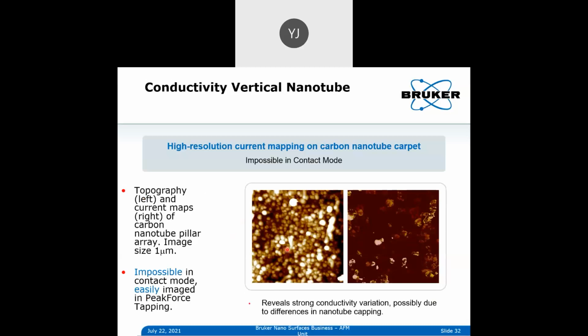Another example is a forest of nanotubes. All these nanotubes you see here are standing facing you, so they are like pillars, right? On top, you sometimes see metal particles like nickel or whatever that's used during the growing process. This is the topography. If you have to image this kind of very delicate sample with contact mode, it's already quite impossible, right? And if you have to do conductive measurements, you can forget about using traditional conductive AFM. But here you can see the conductivity data. You can clearly see not every tube has the metal particle on top. Only some of them still have it, and that's why you can measure the current there. The ones that are not capped don't show any conductivity data.